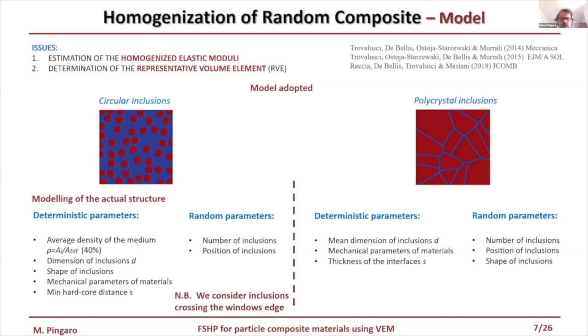For the second model, the deterministic parameters are the mean dimension of the grains, the mechanical parameters, and the thickness of the interfaces. And the random parameters are the number of inclusions, the position of the inclusions, and the relative shape.